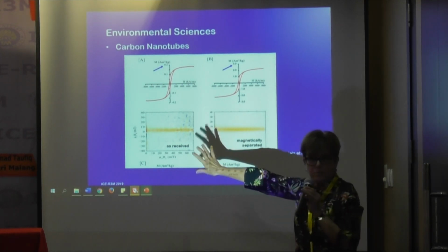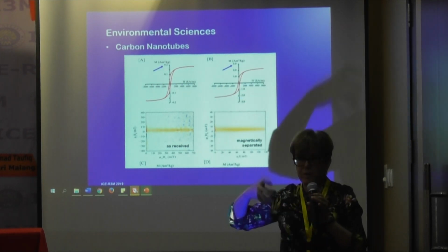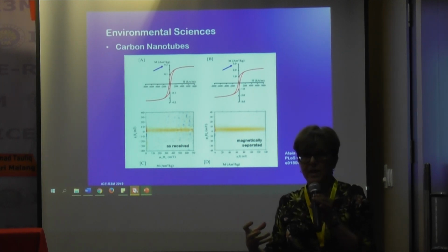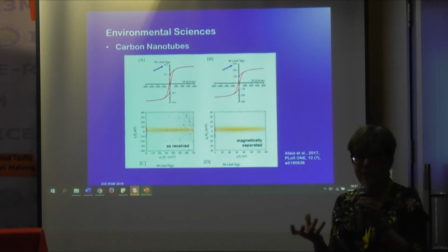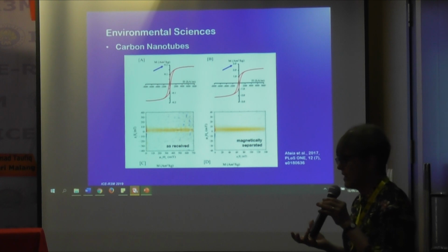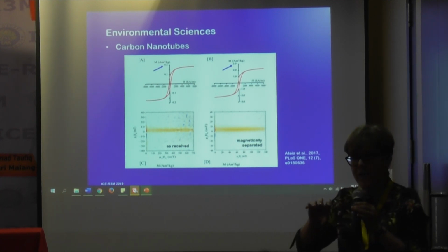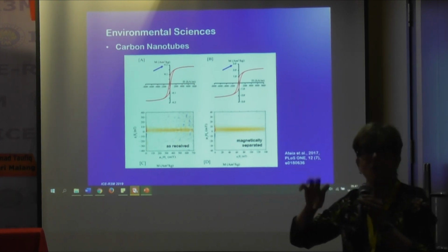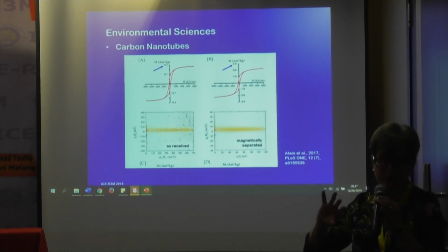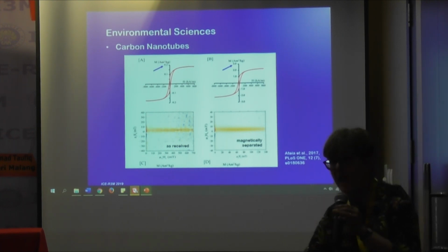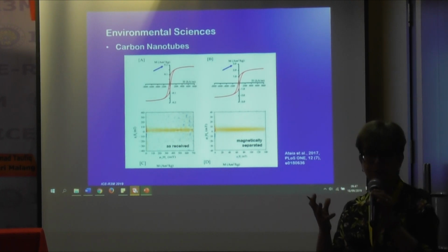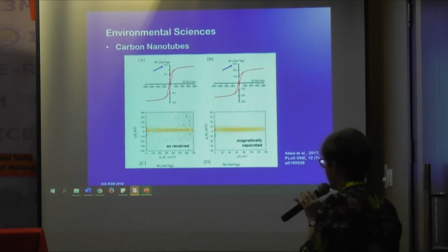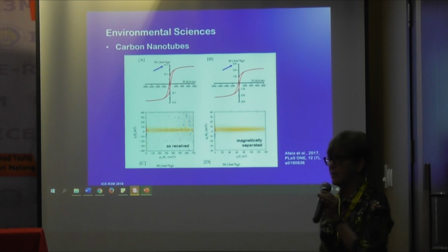First, they just took their nanoparticles as they got them, and they used them to try to absorb out the pollutant, and the absorbency wasn't very high. So they were a bit disappointed, but then they said, okay, why don't I just separate out the really strongly magnetic material and then check how that looks. They found the absorption was very good if they took only the strong magnetic material, and so they wanted to document the difference.